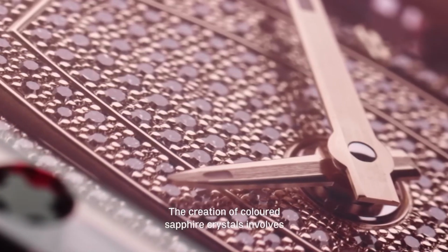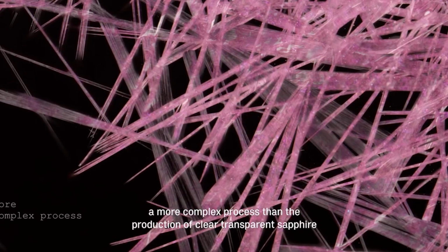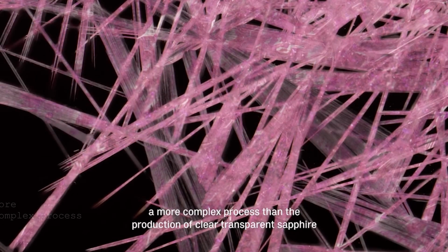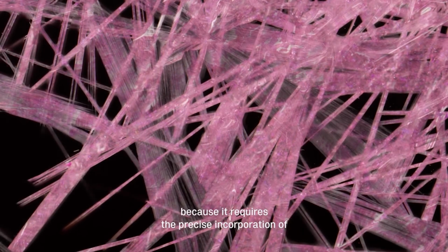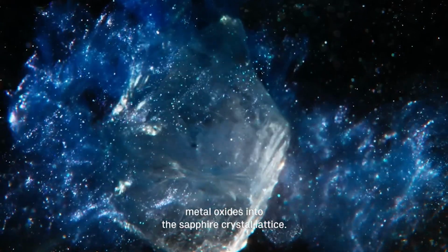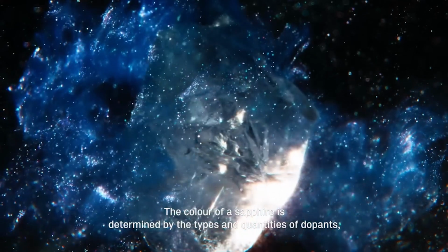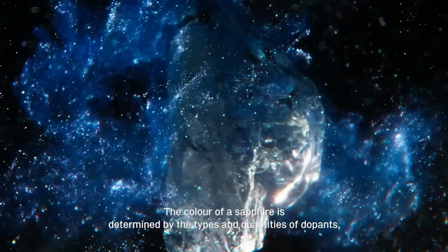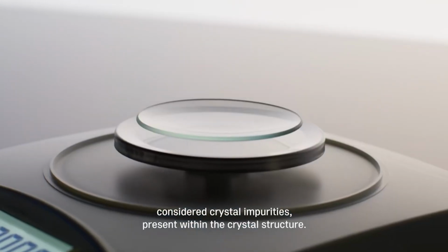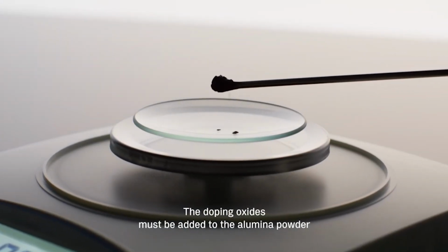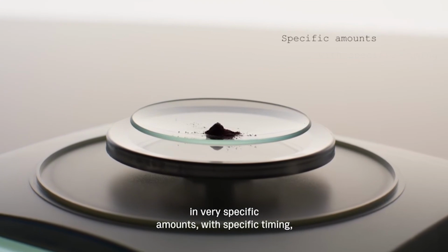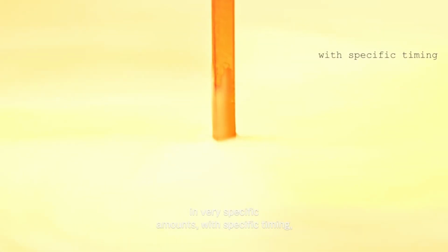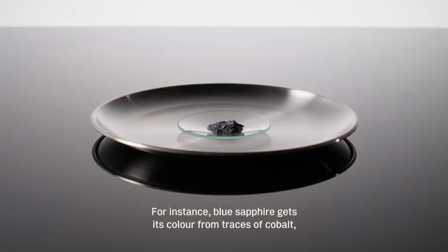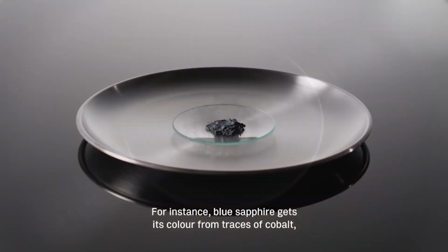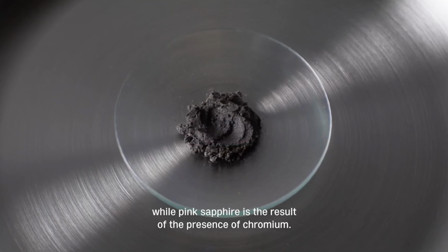The creation of coloured sapphire crystals involves a more complex process than the production of clear transparent sapphire, because it requires the precise incorporation of metal oxides into the sapphire crystal lattice. The colour of a sapphire is determined by the types and quantities of dopants, considered crystal impurities, present within the crystal structure. The doping oxides must be added to the alumina powder in very specific amounts with specific timing, and must be uniformly dispersed during the crystal growth process. For instance, blue sapphire gets its colour from traces of iron and titanium, while pink sapphire is the result of the presence of chromium.